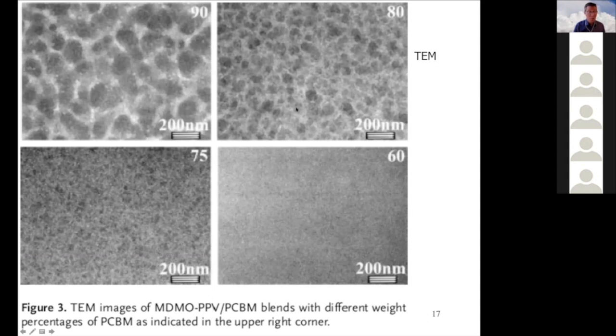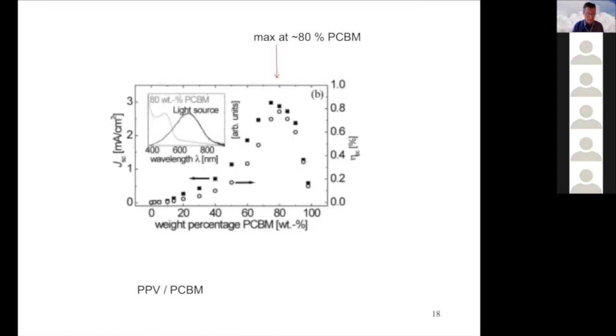That turns out to be the optimal domain size. So you see that at 60%, if there's 60% fullerene in your solution, then you don't see any structure. And at 90%, this fullerene phase is a lot bigger. This nanostructure is correlated to the device performance. Performance of solar cells with 80% fullerene is optimal. So here you see the percentage of fullerene. Here you see some kind of efficiency scale, and it goes up from 60 up to 80. And then if you increase the fullerene content, the efficiency goes down again.